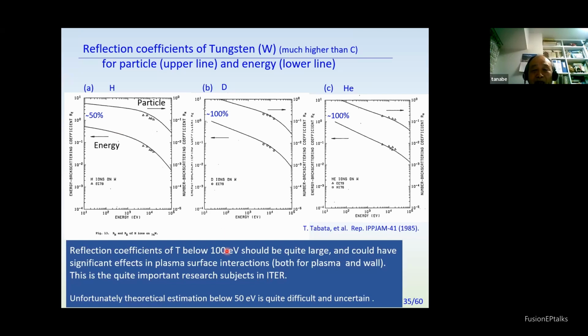It is quite difficult to do experiments on the reflection coefficient, but nevertheless it becomes very high, which could be significant because wall loading becomes less with a high reflection coefficient. Unfortunately, theoretical estimation below 50 eV is quite difficult, and experiments are also very difficult. But please remember that reflection of particles at the plasma-facing wall probably plays quite an important role.